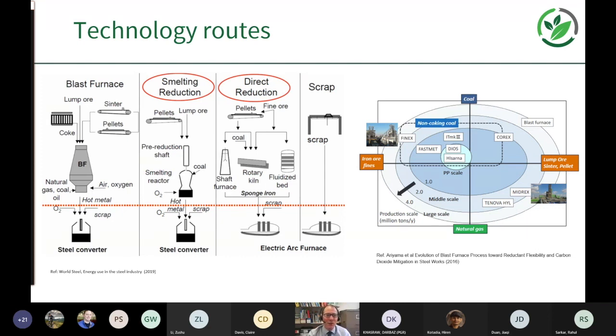So just going through the technology routes quickly again, we've got the blast furnace, and of course this high energy requirement and the CO2 emissions is a carbon-based thermochemical process. It requires processing these raw materials quite significantly before we charge them to the furnace, even before we start to use them. And of course that results in this energy intensity. Then we have smelting reduction. Now, that hasn't got the pre-processing of producing coke and producing agglomerated fines in the form of sinter. And that also produces, like the blast furnace, a liquid hot metal product, which tends to go into a basic oxygen furnace.